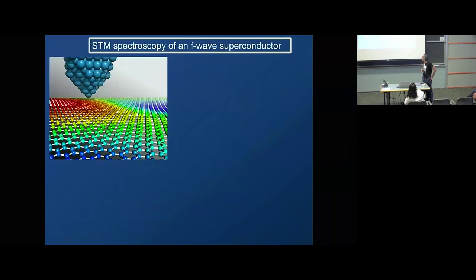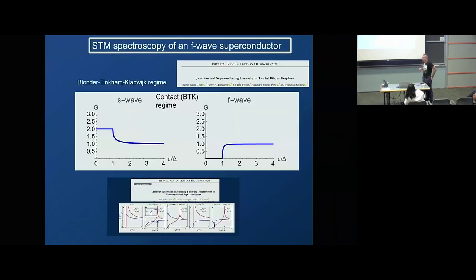It was discussed yesterday. And let me also mention that if you have an F-wave superconductor, it's a non-trivial superconductor, it's not S-wave. And because of that, for instance, you cannot have Andreev backscattering in the contact regime in an STM experiment. That was discussed in this nice paper after experiments by Ali Yazdani.